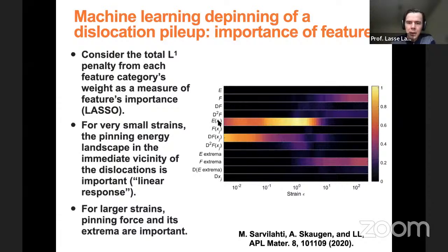So we can see that the pinning energy landscape and the derivative of the pinning force landscape turn out to be the important ones. And then also the extrema of the pinning force landscape are important for large strains. So the importance of these different features depends on strain in this case. I mean, it kind of makes sense. These control the linear response of the system for small strains, while if you look at large strains, when the dislocations have moved a lot, then it becomes more important what the extremal values of your pinning landscape are.